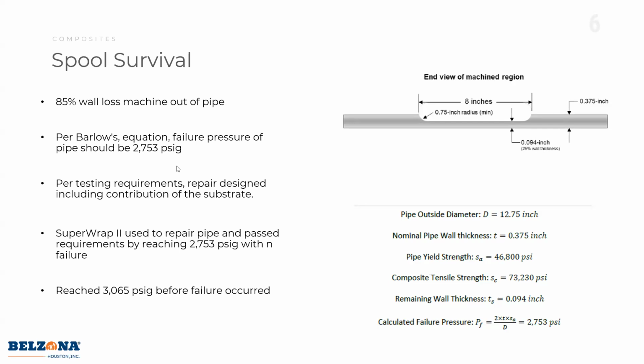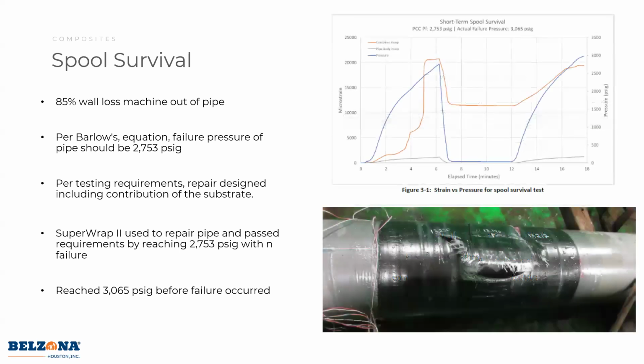So this is one of those pass-fail tests. It has to hit 2,753 in order to prove that we're actually reinforcing the pipe. So we did, and it reached that 2,753. And then once it reached 3,065 psi, the pipe did burst, and along with that came the composite.